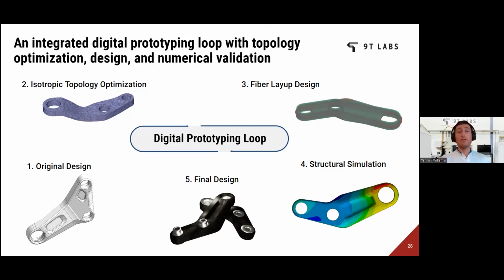Once we have set up a first design, we go into structural simulation, and between steps 3 and 4, we iterate. So that's the great advantage here. We can iterate very quickly. If we see that in the structural simulation, we have some weak points, we can still add some material at a certain point, rerun the simulation up to a validated optimum stage, which then we would generate a G-code, and the G-code is something which is frozen, sent to the printer, and the printer will replicate this code into a real part as much as we want. So basically moving into serial part production. So we see on step 5, the final design.